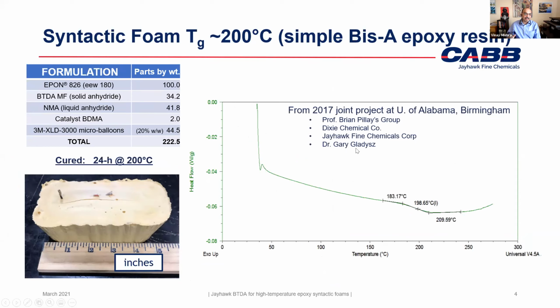And Dr. Gary Gladys, who's been on the panel before here, was my colleague at that time at Dixie Chemical. And in this project, we actually proposed that the system does not use the straight BTDA powder dianhydride, but use it in combination with a liquid monoanhydride. In this case, we used nadic methyl anhydride.